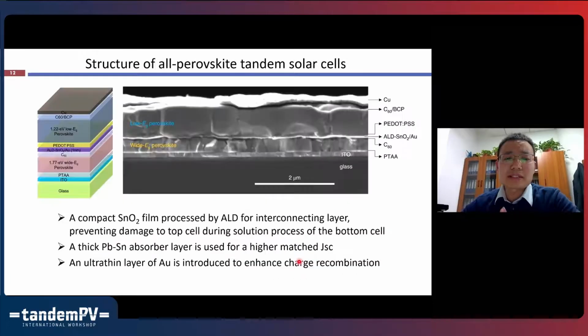So the next step is that we have to use this improved narrow bandgap perovskite to build all-perovskite tandem devices. When we want to make the all-perovskite tandem devices, one critical issue we have to solve is how to make sure the wide bandgap subcell will not be damaged when you do the second perovskite layer by solution processing. At that time, we thought about an idea. Maybe we can use a very thin, compact tin oxide layer that can be processed by atomic layer deposition to replace the traditionally used ITO film, because we don't like the ITO film in the middle of the two subcells, because that will largely increase the shunting probabilities for these tandem devices.